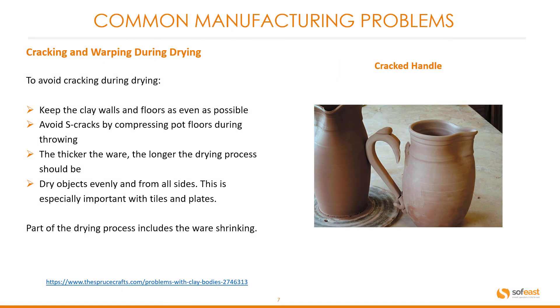Let's have a look at some of the common manufacturing problems. Cracking and warping during drying: to avoid cracking during drying, keep the clay walls and floors as even as possible. Avoid S-cracks by compressing pot floors during throwing. The thicker the ware, the longer the drying process should be. Dry objects evenly from all sides — this is especially important with tiles and plates. Part of the drying process includes the ware shrinking.